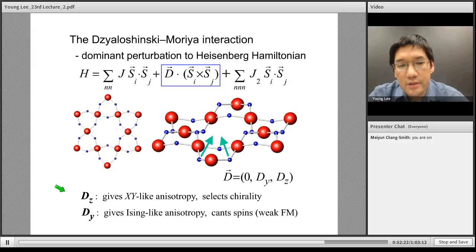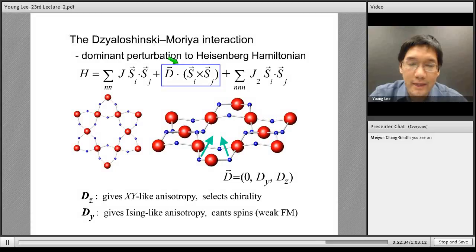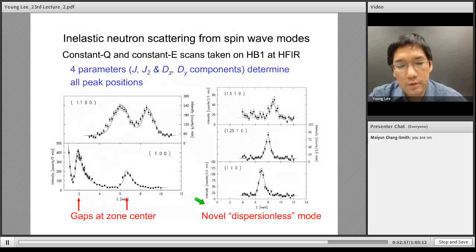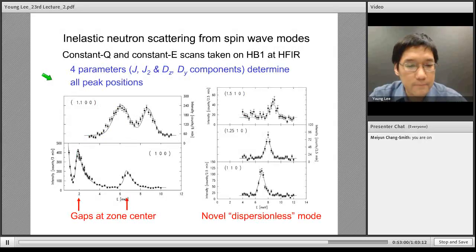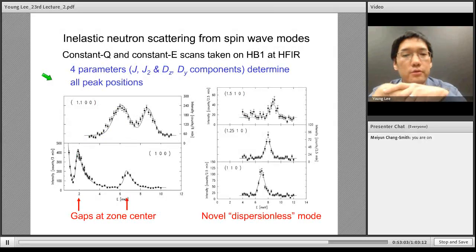So this Dz, if you want to have this D dot Si cross Sj give you a low energy, then having a Dz vector perpendicular to the Kagome plane means you want Si and Sj to both be in the Kagome plane. So this gives you an effective XY-like anisotropy, and it also selects a chirality. And then this Dy component here picks a particular in-plane direction. It gives you an Ising-like anisotropy. It also does some other things like give you a spin canting, and these are some predictions that we have measured. But let me just focus on the neutron scattering.